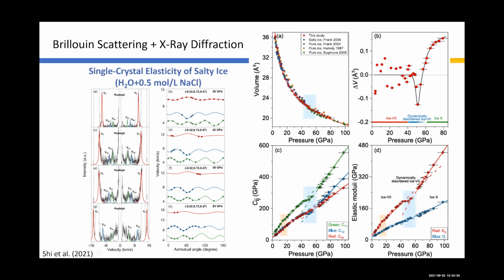We also get the single crystal elasticity of ice X up to 94 GPa. We also use Brillouin scattering together with X-ray diffraction at GSECARS, and we actually track the very small volume change when we go from ice VII to the dynamic disordered ice VII, shown by panel B on your right, top right.